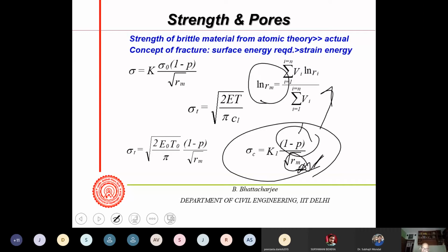This is easy. This already we have found out from Power's model. This we have found out. So E and T are for pore-free solid. Higher E, higher T, strength is more. Higher porosity results in lower strength, higher water-cement ratio, higher porosity, that's what we have found out. Larger the pore sizes, lower the strength. Higher water-cement ratio, larger is the pore size. Why? You can see that now.